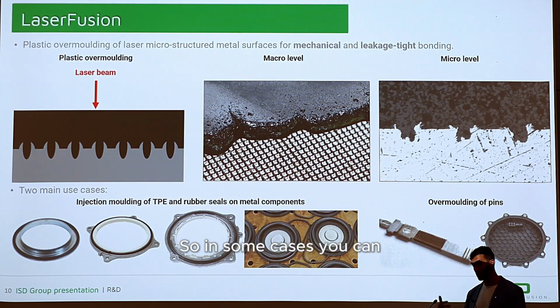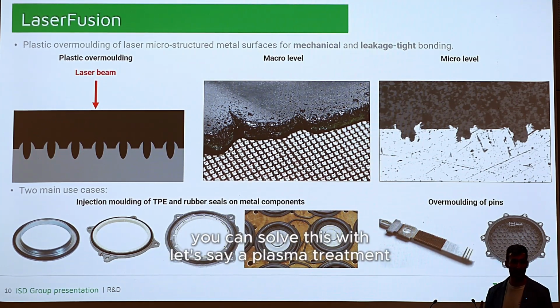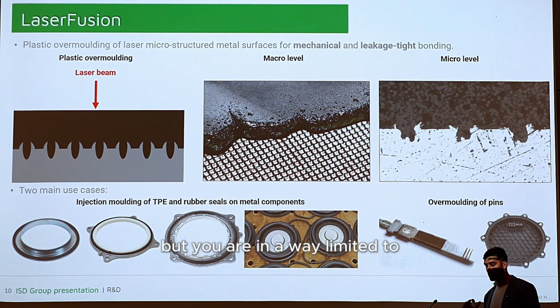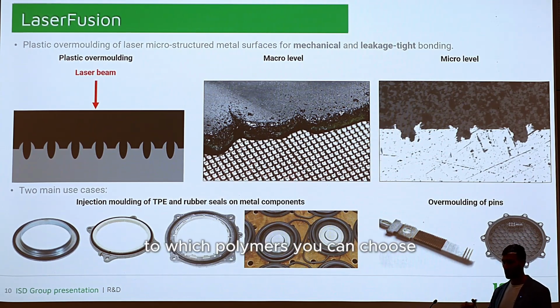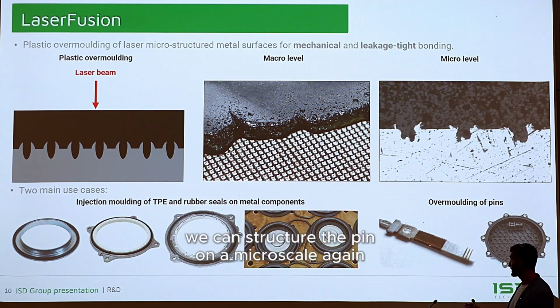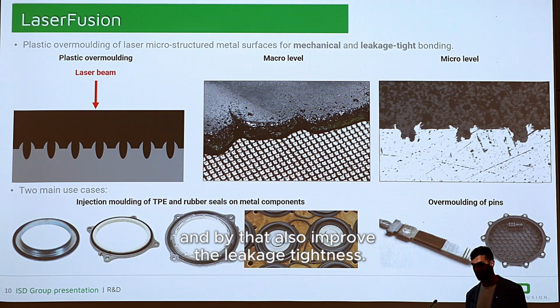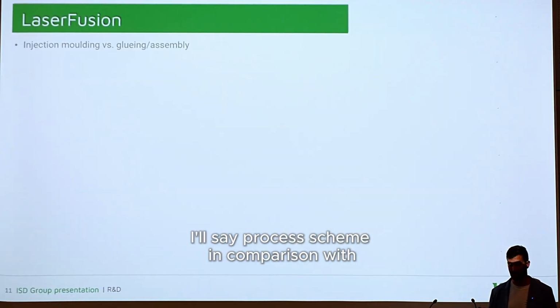So it will not be leakage tight. In some cases you can solve this with, let's say, a plasma treatment, but you are in a way limited to which polymers you can choose. In this case, we can structure the pin on a micro scale again, we overmold it, and by that also improve the leakage tightness.